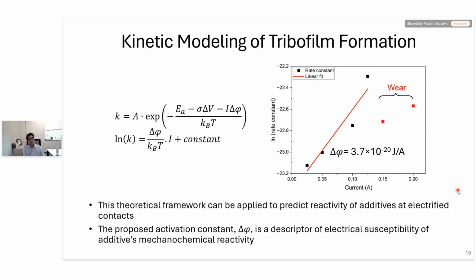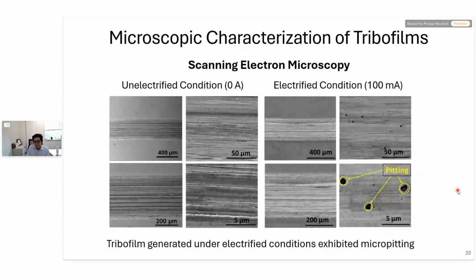reactivity. We also looked at the tribofilm morphology by scanning electron microscopy. Under unelectrified conditions, 0 amp conditions, we saw typical striations that are seen on running tracks because of shear stresses at these sliding contacts. So, a very striated morphology.